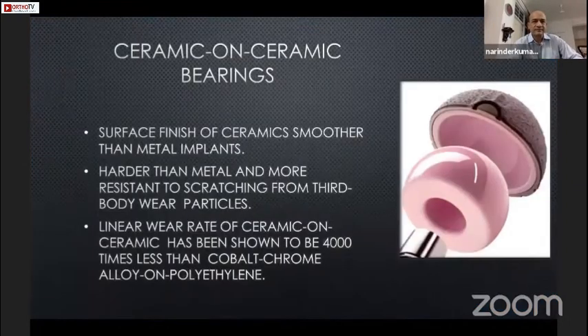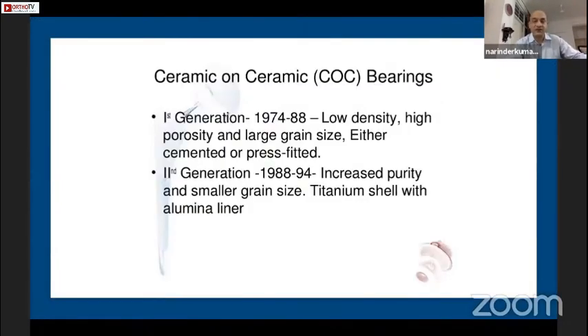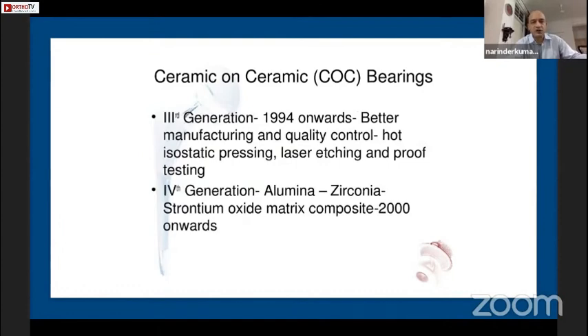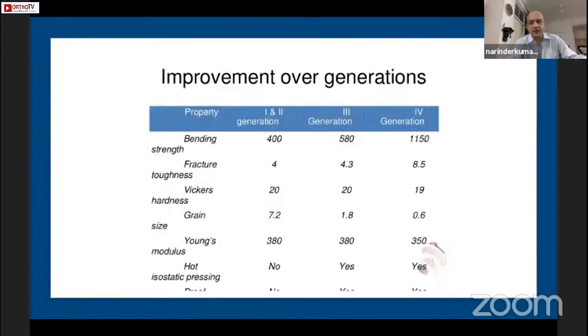Well, surface finish of ceramics, we know that is much smoother than the metal implants. They're harder than metal, they're more resistant to scratching and third body wear, and the linear wear rate of ceramic on ceramic is almost zero. So they should be actually surviving forever, but they do not, because they do have their issues, which were resolved from first generation to second to third to fourth generation now for the last 20 years. The fourth generation ceramic is what we call as delta ceramic now. These improvements are fairly technical, and if somebody wants to use them, they can ask for my presentation. I can send it over, happy to.